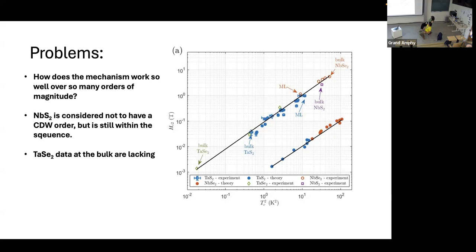Yes, Tara, you're saying something? The question is whether it has any relevance. If you ask what can tune superconductivity, then even if you have a conventional superconductivity, you still need to take into account the Coulomb interaction. If you change the screening of the Coulomb interaction, it still changes the Tc. So yes, that might change. Okay, so screening of Coulomb interactions, it's interesting. It would depend in a way on carrier density, I guess.